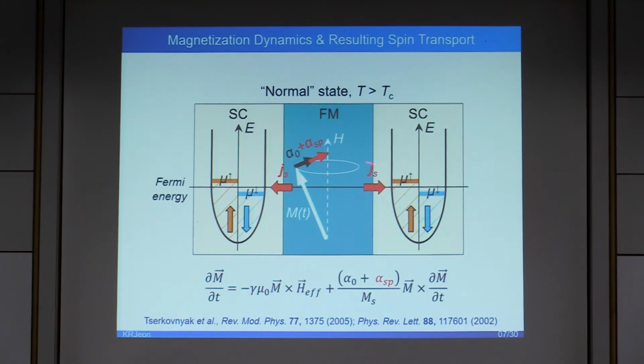When the superconductor is in the normal state above its Tc, the steady-state magnetization precession of the ferromagnet can inject pure spin current into adjacent superconductors via dynamic exchange coupling across the ferromagnet-superconductor interface, so-called spin pumping. And the absorption and dissipation of spin current in the superconductor leads to the enhancement of the effective Gilbert damping of the ferromagnet,